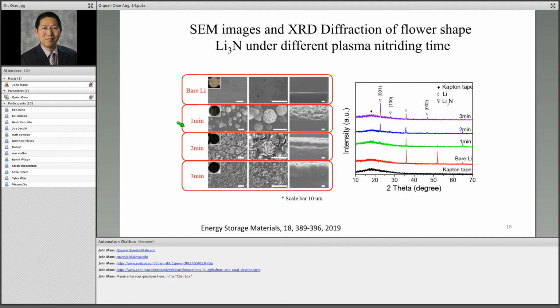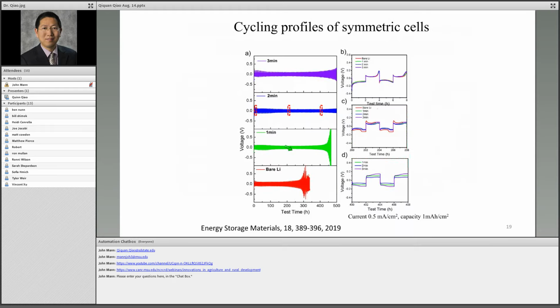And then you can optimize the amount of lithium nitride growth on the surface, and you can check that by seeing the XRD here. I will not go into much detail. You can see that at 2 minutes, in this cross-section under the scanning electron microscope, you have very uniform lithium nitride growing on the surface. And then you use this to fabricate the batteries.